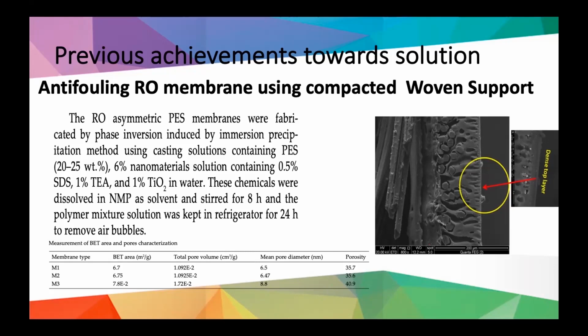So if you go through the effect of the structure of this support, in this study we have a comparison where we compare the woven structure and the non-woven structure with the unsupported membranes, which means the membranes were cast on a glass plate. But in other words, we can't use membranes cast on glass plates for getting spiral wound industrial modules.